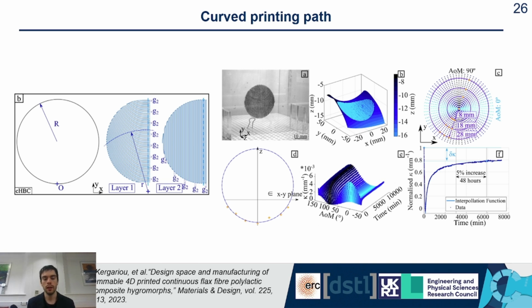Another aspect that we wanted to look at is curving the printing path. So instead of having straight fibers, we wanted one of the layers to have curved fibers, and see how this would impact the formation of the specimen. So we reprinted the printing path on the left, conditioned between 11 and 98% as usual, and then obtained its 3D shape with DIC, as with the previous specimen. It's a circular specimen, so we define what we call angles of measurement, which are different angles in the radii of the specimen, in which we obtained different points and then the circle that we used to obtain the curvature for these different angles.